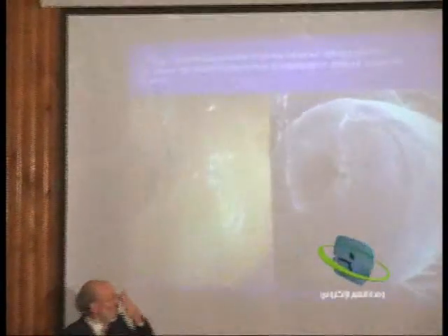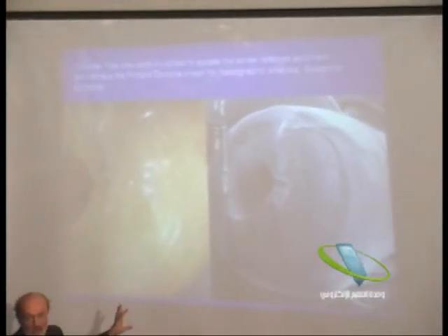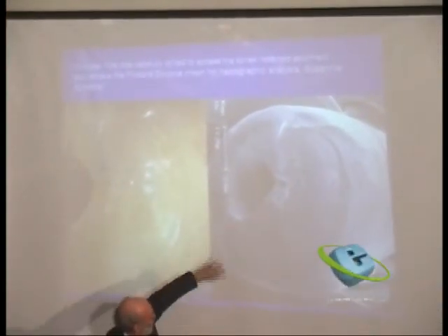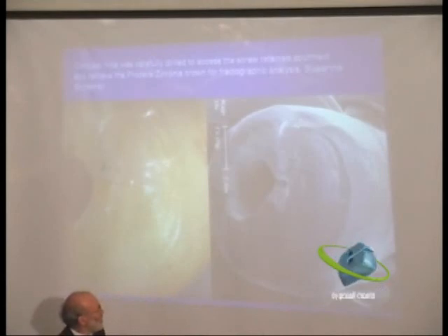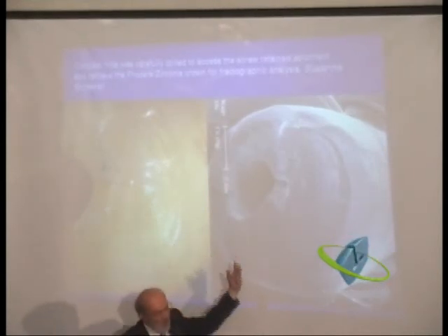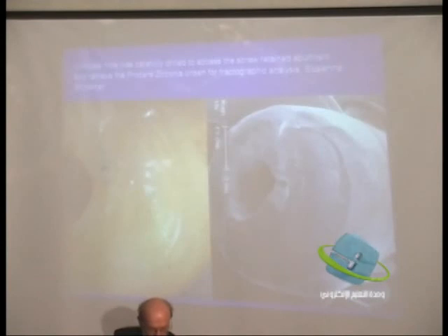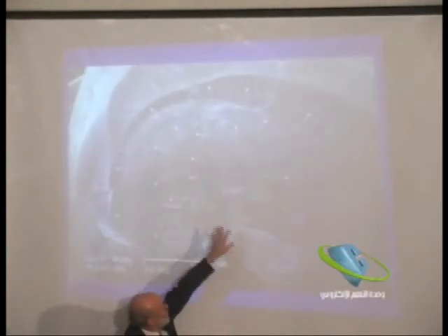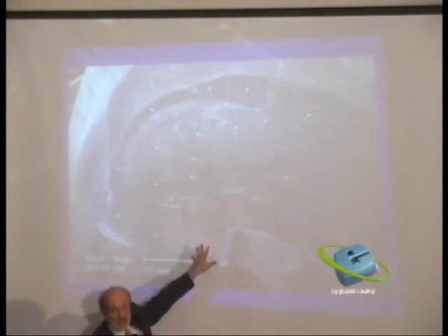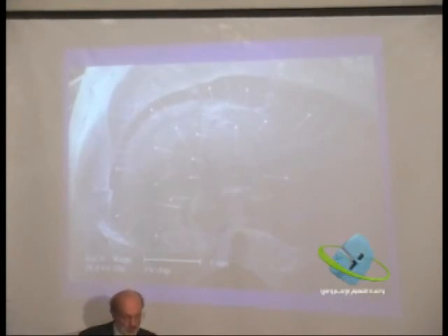Now, is this occurring in other systems? Yes, here is another example from Suzanne Scherrer at Geneva, and this is the case of a complete cusp that completely broke off that material. Again, on zirconia, you see this complete crack growth that is occurring in that system. It's not initiating at the surface, and again, she's done a complete fractographic analysis of that system, showing that the crack is starting in here, then growing within the system, and there's tensile residual stress, and then chipping out afterwards.